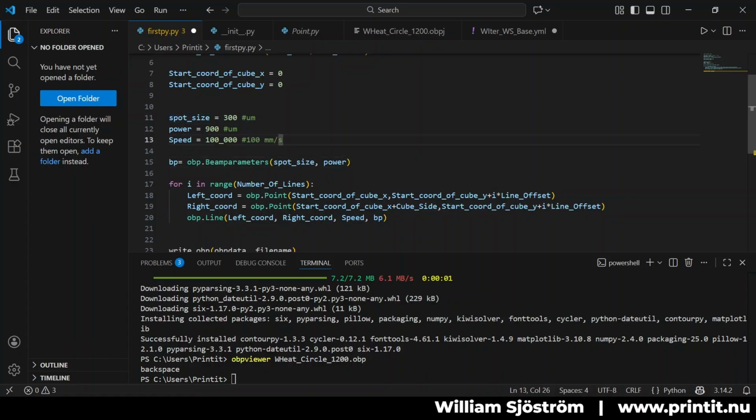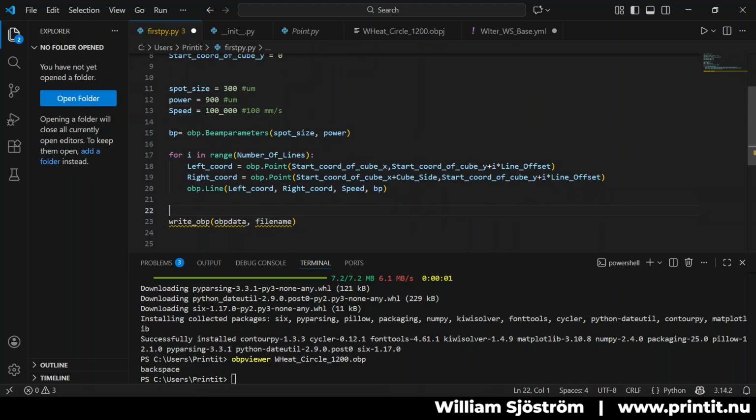So a quite slow process, but should be possible to do some of the difficult to melt steels and so on in that range of parameters, I think. And of course, this is something you need to try out for your materials, either check publications or do some experiments where you have one cube with each setting, or copy our approach with doing gradient development, and you will have some idea of what to have here to get solid materials.